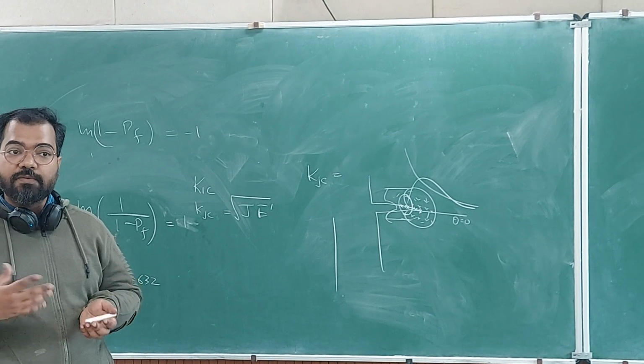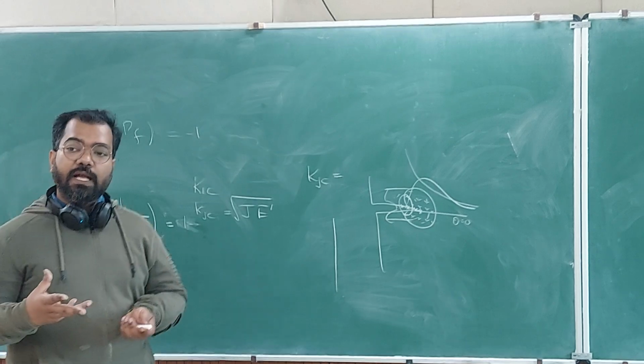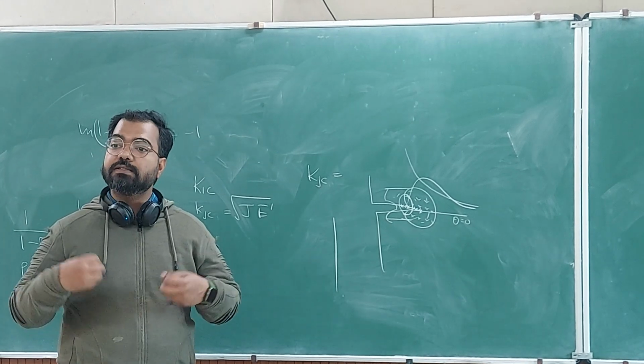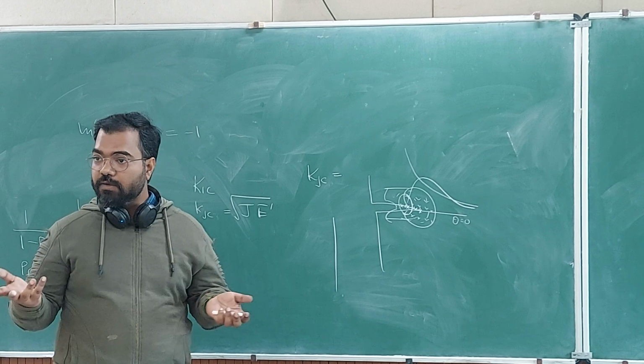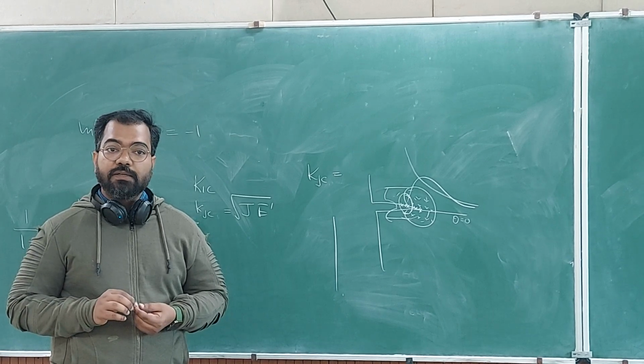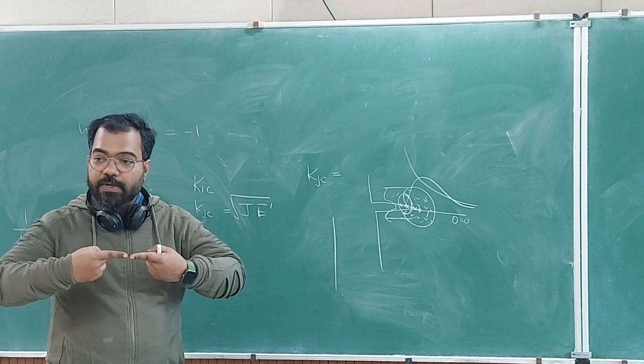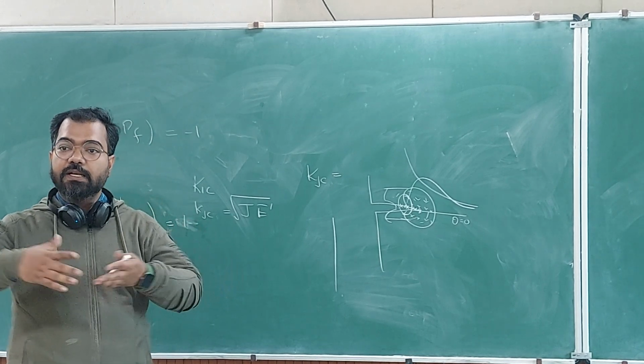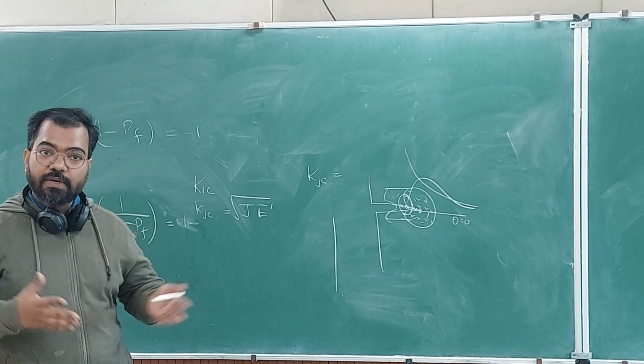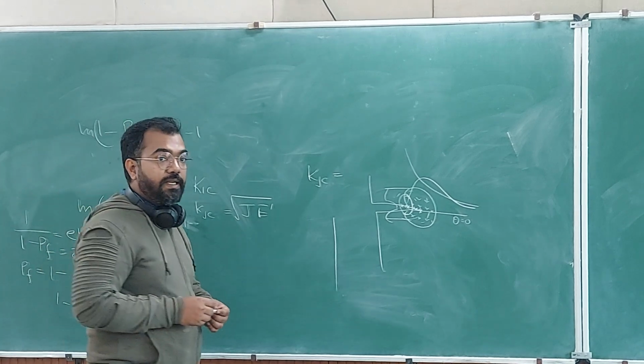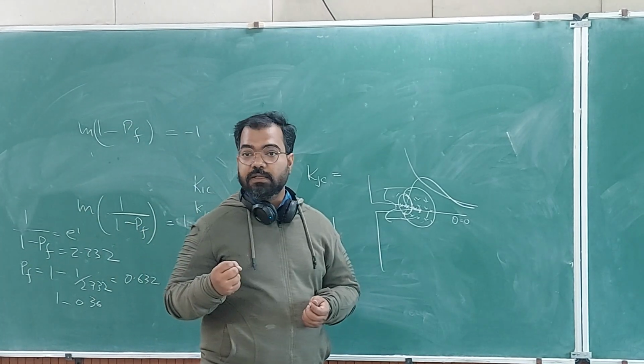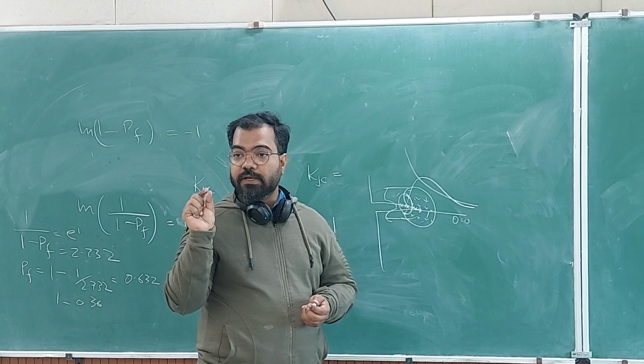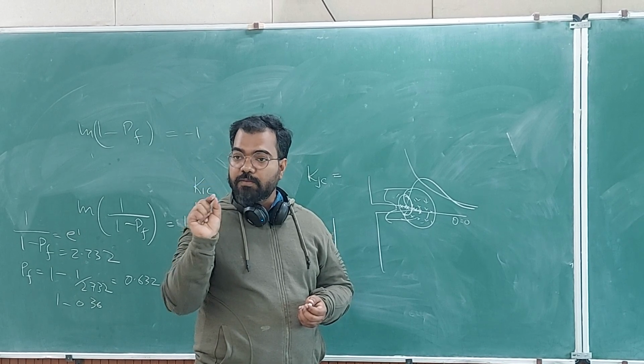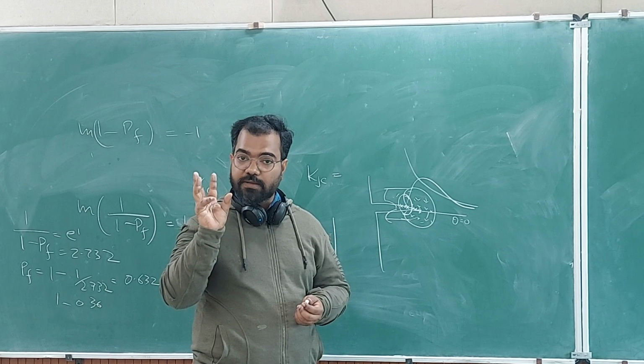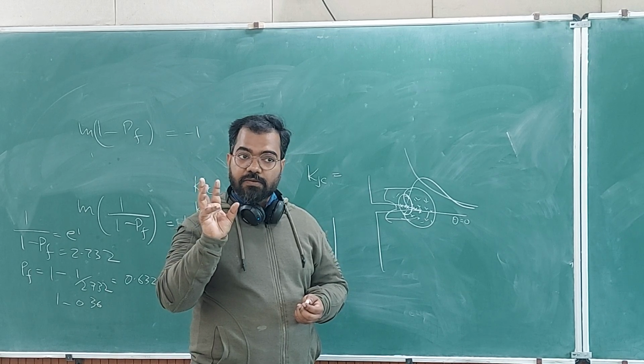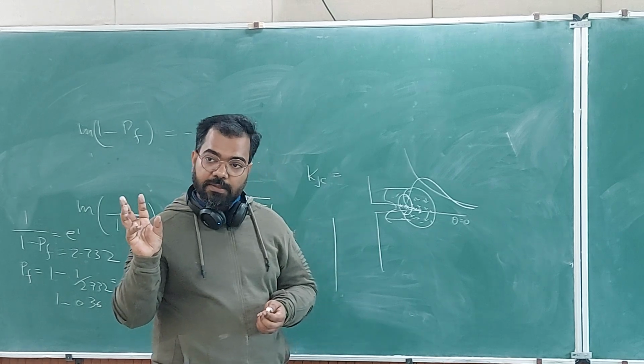If 4 of them or 5 of them create microcracks, and those microcracks locally increase the stress even further because those are microcracks, then those microcracks will just open up and join each other, and they will become a big crack and open up, and you will have a brittle fracture. If the matrix can have some ductility, then the matrix will deform around these microcracks and they will become voids. So ductile damage will happen.